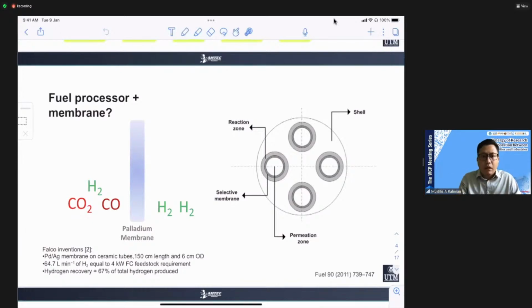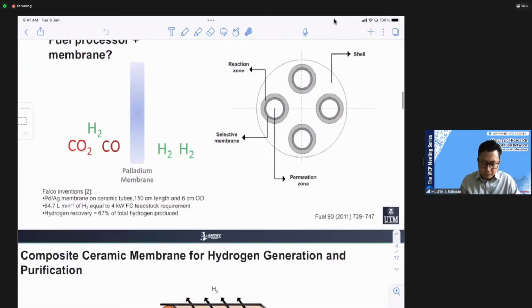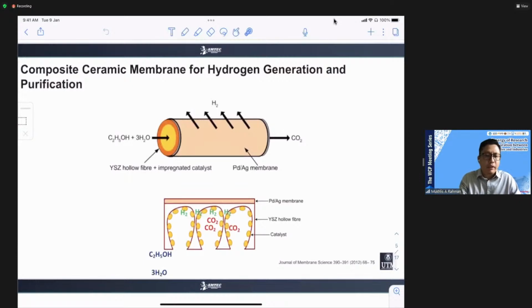Based on this, Falco used a ceramic tube of large diameter. So I think that gives us an idea to investigate the possibility of using a ceramic hollow fiber to replace the ceramic tube. So we came up with what we call a catalytic hollow fiber membrane microreactor for the production of hydrogen. In this system, we put the palladium membrane on the outer surface of the ceramic hollow fiber, whereas on the inner surface we put the catalyst for hydrogen generation. The finger-like structure that appears in the cross section of the ceramic hollow fiber, we put the catalyst inside it. The approach is that hydrogen is produced in the inner surface, and then due to the partial pressure difference of hydrogen, it will diffuse out through the palladium membrane.